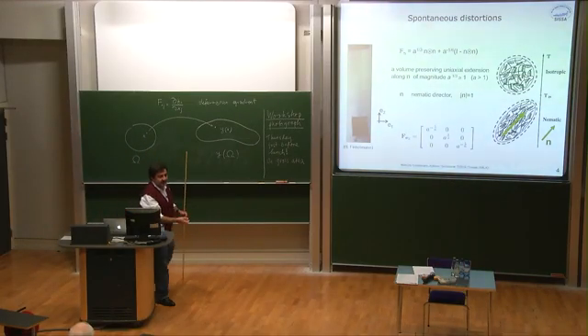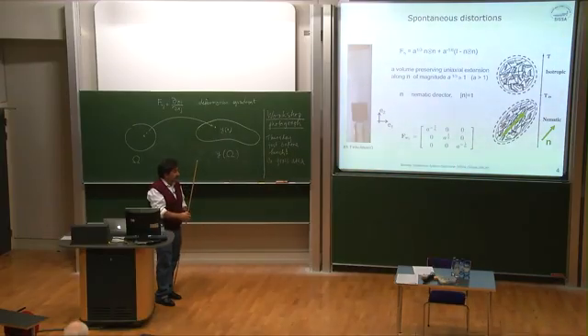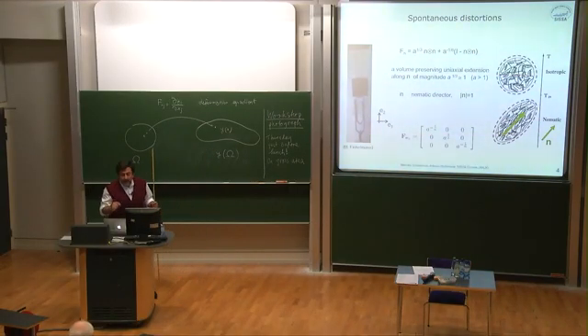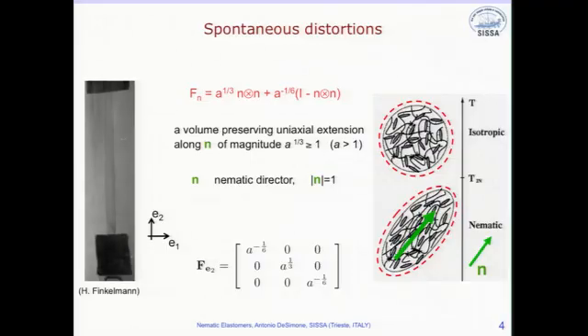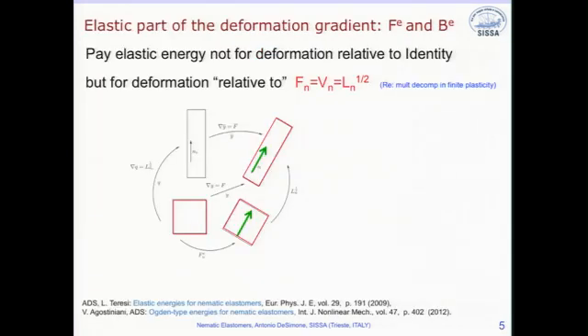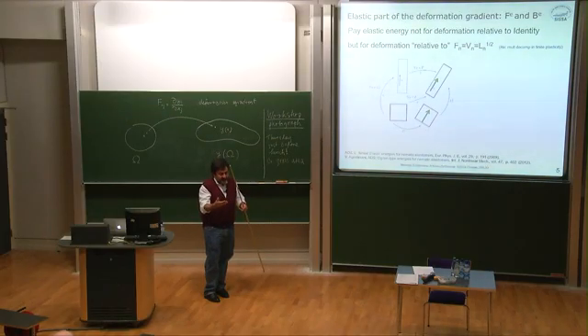What is in rubber elasticity is the identity, so to speak. So the material stays there. That's the undistorted configuration. In this system, it's a rich set of zero energy states. Now we have to build an energy that tells us how much we pay, what is the elastic cost of deviating from this preferred state of distortion. Okay? So let me borrow an idea, so here I'm telling you the idea first in nonlinear kinematics and then in linear kinematics. In nonlinear kinematics, the idea is borrowed from plasticity. And when you do plasticity in finite deformations, there is a notion of deformation relative to a preferred state or to a relaxed state. So you have something occurring at the microscopic scale that sets the state in which the material likes to be or goes back when you unload it. And so all the energy, all the elasticity happens in the deformation relative to that state.